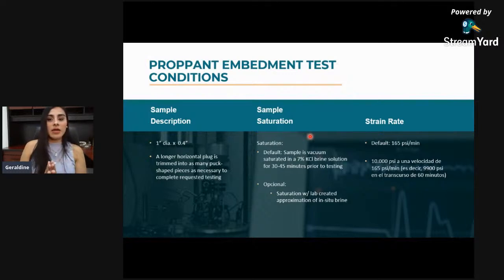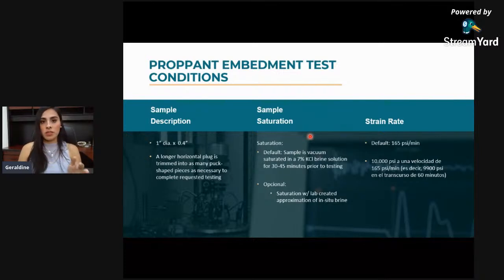Proppant embedment is another test. The sample description that you want for this test is a sample of 1 inch diameter by 0.4 inches of length. This means you also need only a little bit of sample. It's like a cookie or a disc of 1 inch diameter. You get this sample from a horizontal plug. Again, you trim this plug, and you get all the necessary pieces that you need in order to get all your project done.